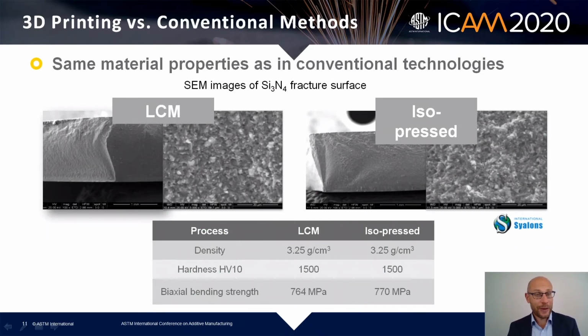So here you see also a comparison between the LCM technology and the isopressed technology, and what you see here is that there is no difference. So this is a silicon nitride, and here you see the microstructure as well as material properties, and you see the microstructure is the same as well as the material properties are also the same. So it's really comparable. This is nothing where additive manufacturing cannot deliver what traditional forming technologies can deliver. So it's something where we can say the state of the art is that we can achieve the same or at least very similar properties as in conventional forming.